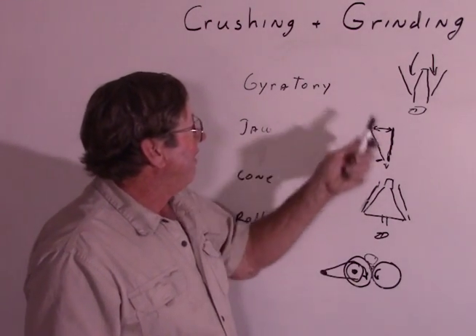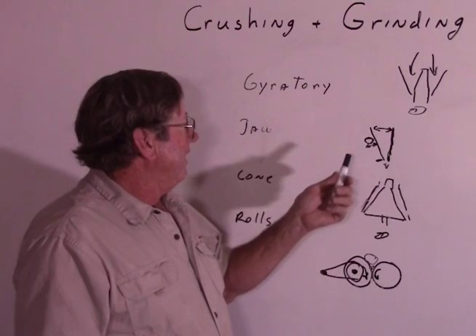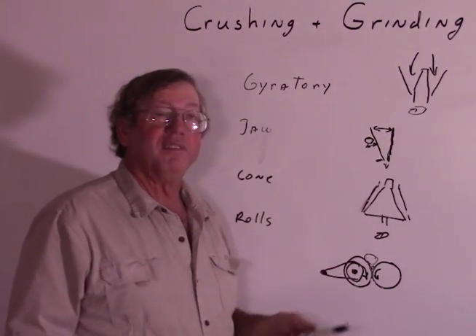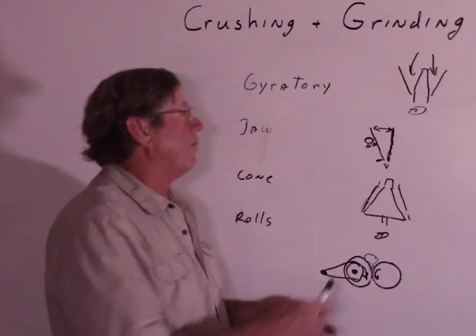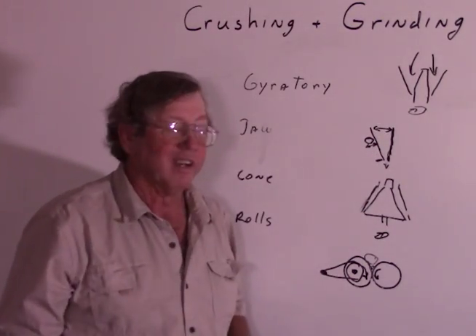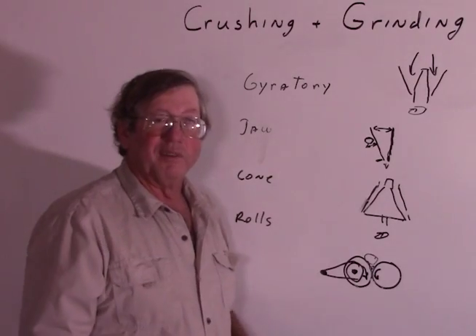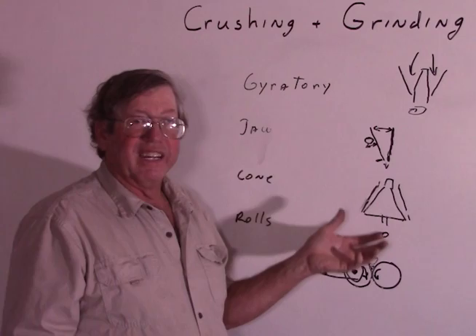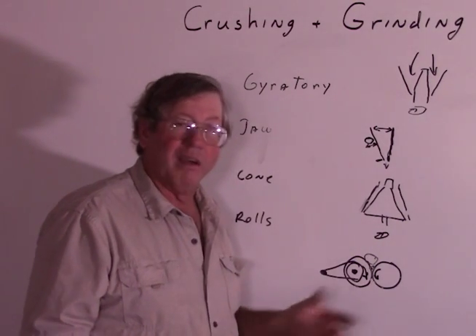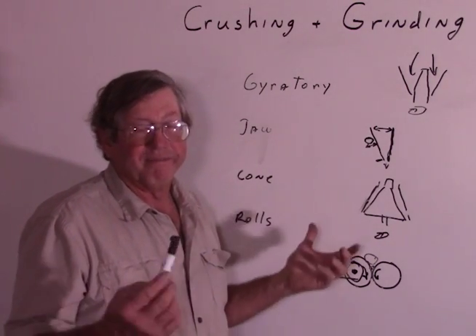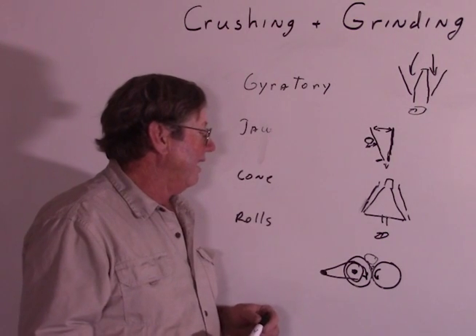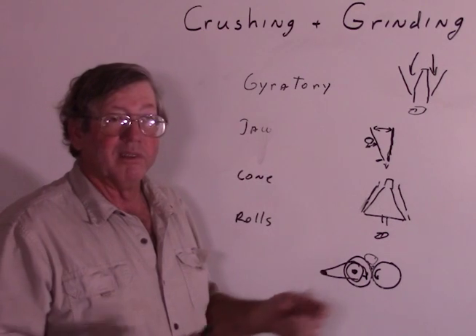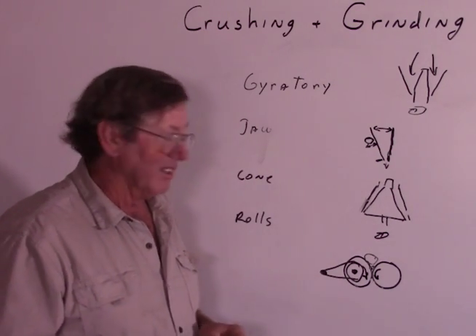All of these, depending on how sticky the material is, may or may not work well. If it's too sticky, you may have to do water flushing — pour so much water through that it turns everything into a thin mud, turning it into a slurry as it crushes so it won't stick. That creates complications, so if you don't need it, best not to do it. In our case, using hard rock, a jaw and a roll produces sand and powder fairly effectively.